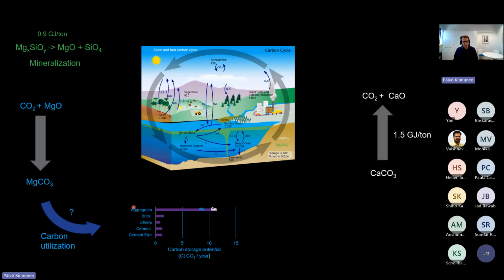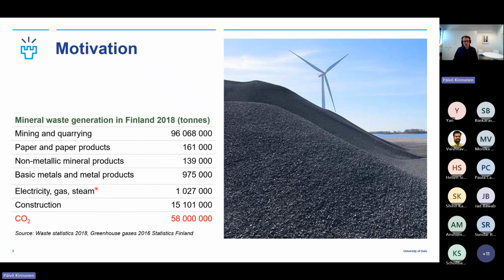Then the next question that could be asked is, okay, what about the raw materials? Is there enough raw material to do this with this proposed mineralization and utilization route? So one of the motivations for our group, actually, for the past 10 years has been this. There are a lot of big mineral waste streams in Finland. There's mining waste as the biggest, and there's magnesium silicate containing mining residues, or mine tailings, as they're called, which are already finely ground, which are the sort of prime starting material. And here I've also put the CO2 emissions, and they are about the same volume. And so it turns out that there are enough magnesium silicate sources around the globe, and they're quite evenly distributed. So this is not an issue.